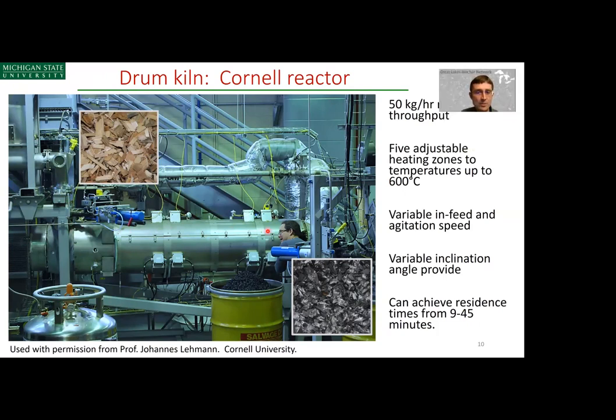There are 5 adjustable heating zones, and you can achieve temperatures up to about 600 degrees C. There's a variable in-feed agitator connected to a number of paddles, and those paddles push the biomass through the barrel.